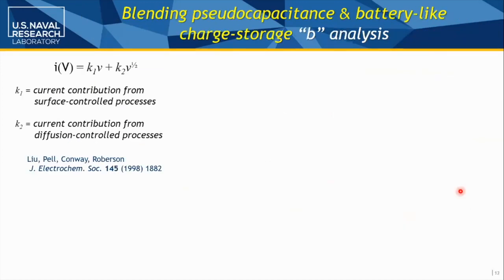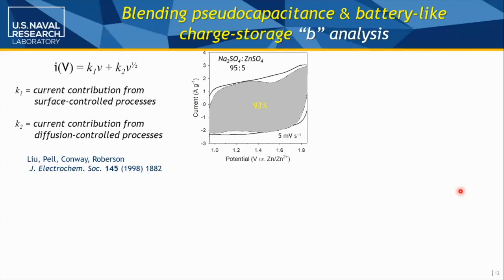So people in the battery world for too long now have been using a deconvolution of that current voltage curve, assigning the surface-sided pseudocapacitive-like to a linear sweep rate, that's the K1 nu, plus the more semi-infinite diffusion for ions that would have to go into the solid state as in a classic battery. And so you'll see the voltammetric curve deconvolve to how much of it is capacitive, how much of it is battery storage.